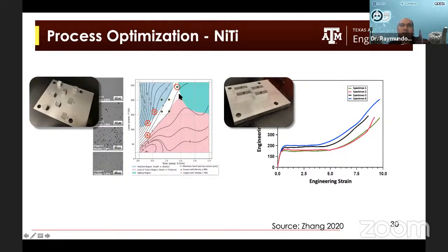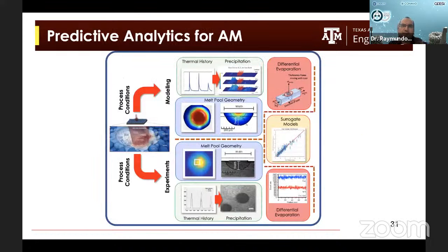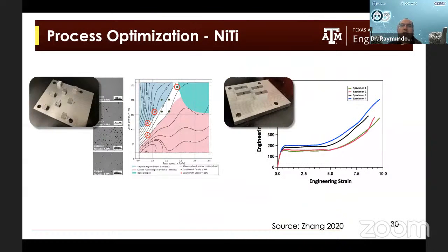We found the printable region. We then printed some coupons in these different printing conditions. And then we were able to verify that they had no porosity and had good superelastic behavior. Now, so we know how to find the sweet spot in processing space. So then we can do, for example, tailoring of the process conditions for the printing.